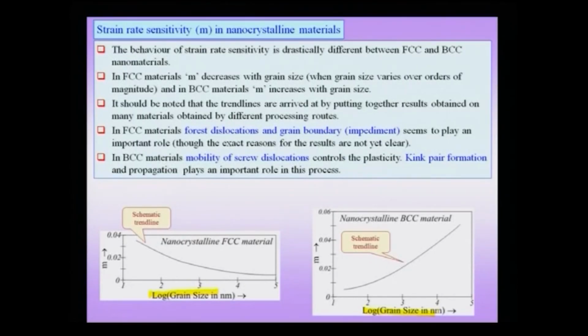If I plot strain rate sensitivity as a function of grain size, and now I am in the nanoscale regime, and of course, I am plotting the log of the grain size, you notice that for FCC nanocrystalline materials, the strain rate sensitivity decreases with an increasing grain size. On the other hand, suppose I talk about a nanocrystalline BCC material like iron, then I notice that the strain rate sensitivity actually increases with an increase in the grain size.